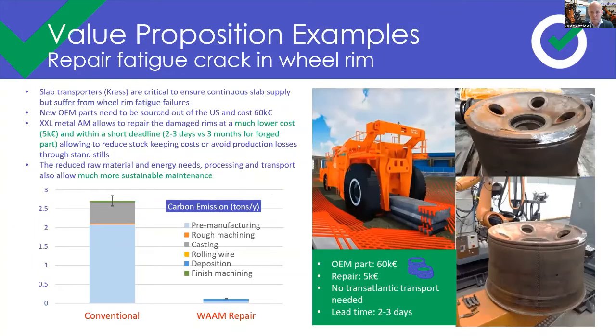Now let's make this a bit more tangible through a couple of examples just to frame the situation a bit clearer. This is an example of a wheel rim from a slab transporting vehicle which is used in the steel industry. There was a fatigue crack in one of these wheel rims, which was actually putting the vehicle out of use. And these are actually quite critical vehicles in the steel industry. If they're out of use, the entire downstream operations can be hindered by that. So they're quite essential. What we did is basically we removed the fatigue crack from the rim by grinding, and then we filled the groove that existed with new virgin material, which had the same properties as the original material.